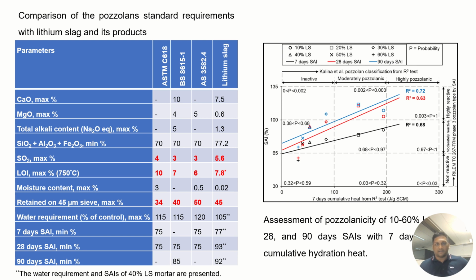So the 7, 28, and 90 days strength activity index of the specimen are plotted with R3 test data, and we can see a good correlation on the right side with R square 0.63 to 0.72, where the RILEM considered 52 pozzolans to find out the same R square value and found 0.83.